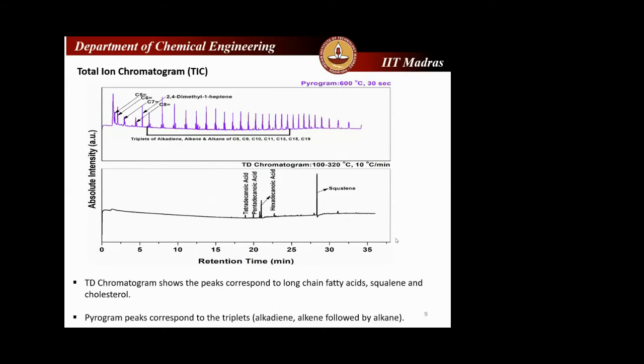In this range, whatever unreacted monomers, solvents, additives, or low molecular weight compounds are present in that sample will come out in the thermal desorption range. After that, if you directly subject it to pyrolysis, all of these would come out in a single chromatogram. So to avoid interference from the complex environmental sample, this will be useful. First, these compounds will not interfere in pyrolysis.